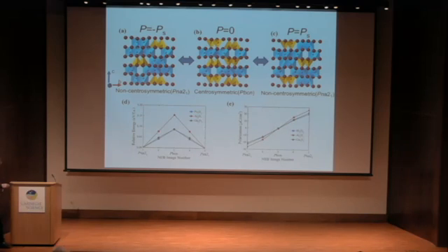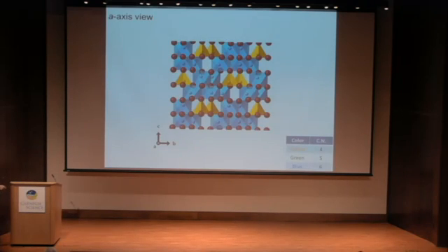In the case of kappa alumina, this is about 0.15. In both the epsilon ferrite and epsilon gallate cases, the energy was found to be 0.09 electron volt. And maybe this is fairly small compared to what was expected. Anyway, this is the structural change during the polarization switching, viewed from the a-axis.